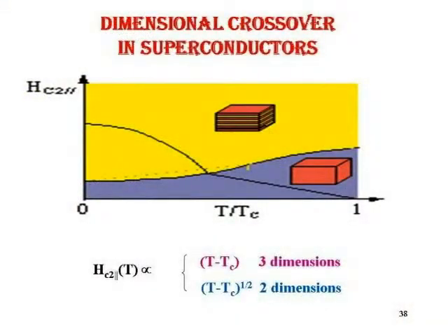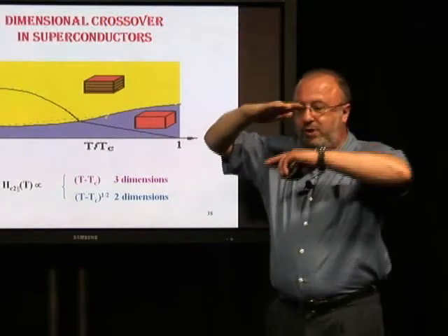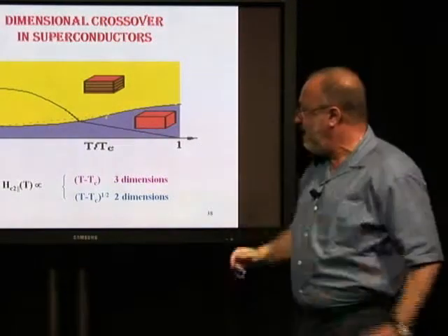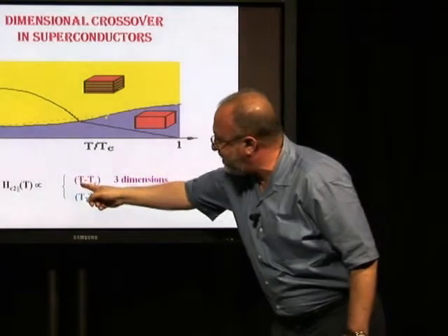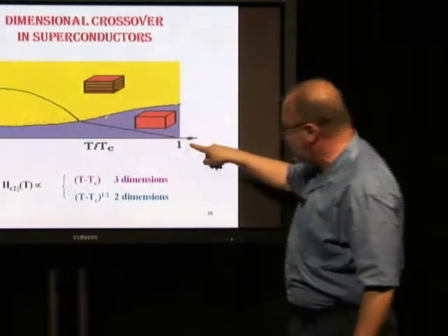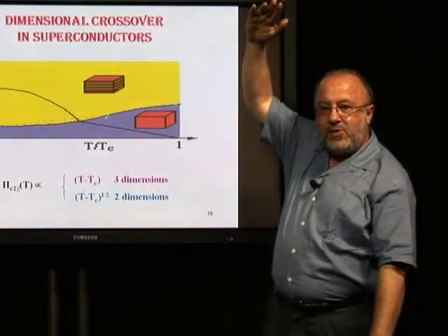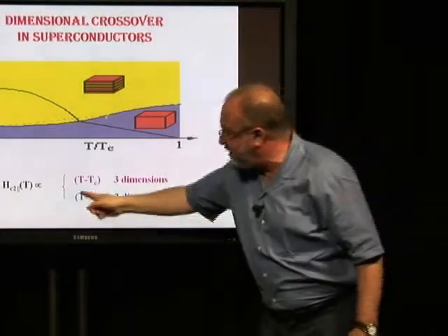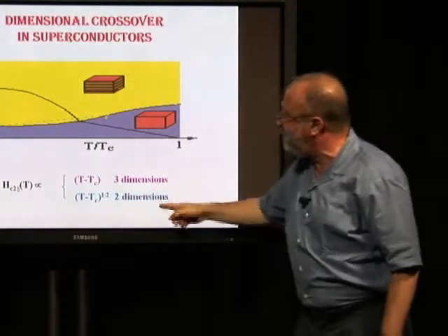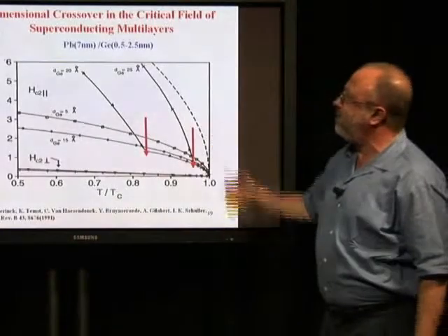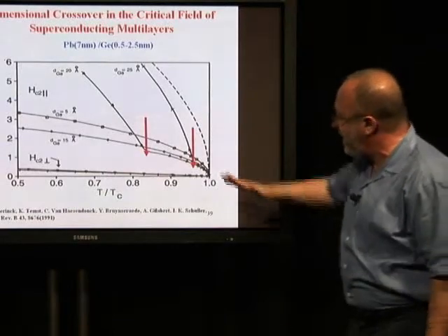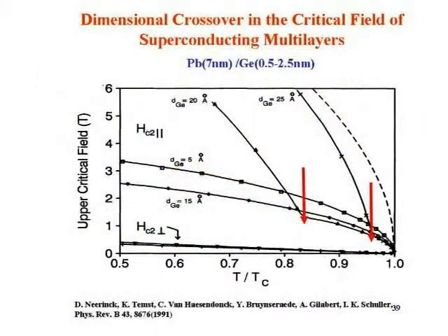This leads to another interesting thing. If you measure the superconducting critical field as a function of temperature, in a region in which the layers are coupled strongly together, the material looks three-dimensional, so the dependence is linear, like this. However, if you separate these layers enormously by some other material in between, then the dependence becomes square root-like, two-dimensional-like, which is like this. This effect was observed in a bunch of extensive studies that we did, where you go from three-dimensional to two-dimensional behavior, in particular for lead-germanium superlattices, which was again done in collaboration between the two groups.